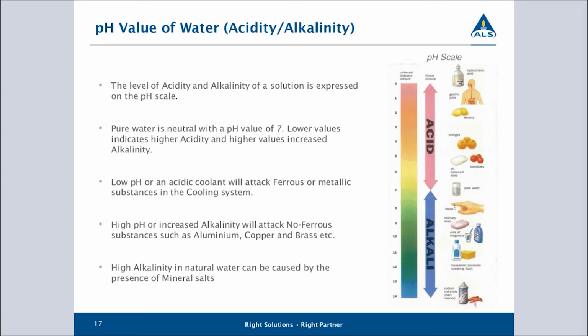All right, pH. Water that we start with has a pH of 7. We will put additives into this coolant. Generally, those additives tend to be more alkaline. And so what we see is that the overall pH value of a coolant tends to rise above 7 to somewhere around about 8. So most new coolants, when we test the pH, will test somewhere around about 8 on the pH scale. And it should be stable.